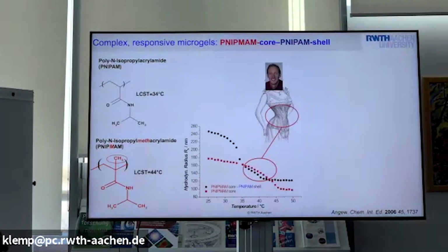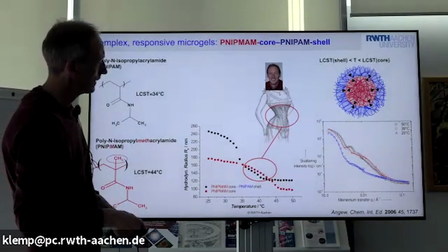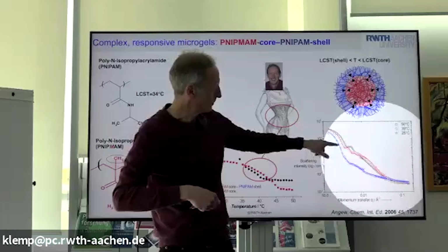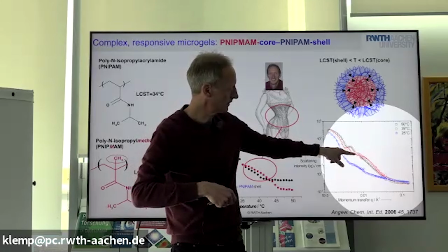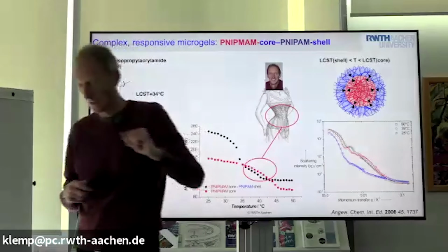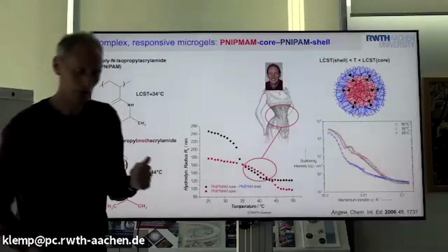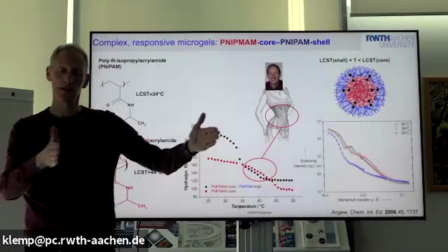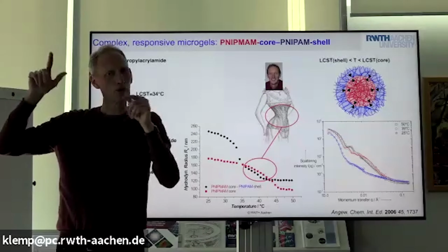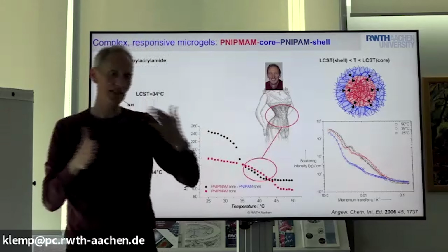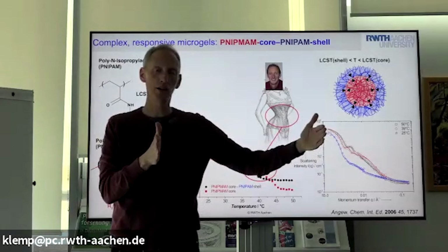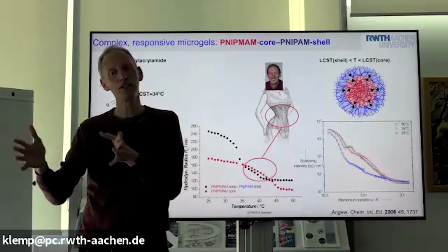Yeah, maybe I show one example again. When we have these types of scattering curves, the position of the minima is very sensitive. The most important parameters that we typically have are the size plus what we call the fuzziness of the surface. And these are different length scales. Let's say the size is something like 100 or 200 nanometers, and the fuzziness is something like 50 nanometers.